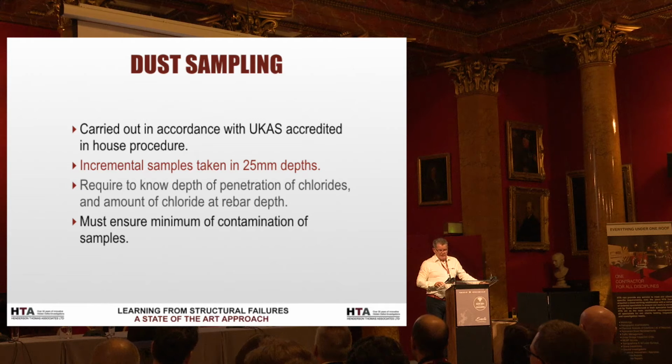Again, we carry out under our UKAS accredited in-house procedure. We take incremental drillings down to normally around about 100mm. The reason being they're incremental is the chloride ingress is normally of an ingressing nature from de-icing salts or from a marine environment. Hence, generally, you'll find that the highest level of chloride will be on the surface, normally diminishing with depth.